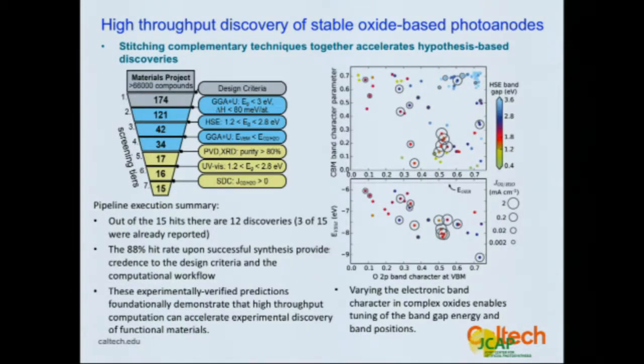And so, one more point on this: we were able to show, from a different screen on a wider variety of complex oxide-based photoanodes, starting with more than 60,000 compounds, we were able to go down using theory, shown in blue, and then experimental screens in red, to get 15 hits, meaning 15 candidates that had the correct band gap, were electrochemically stable, and exhibited signs of water oxidation.